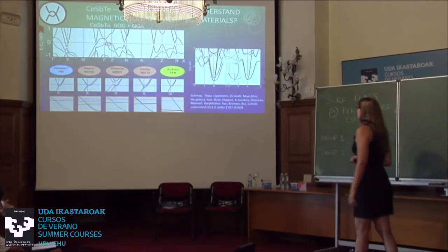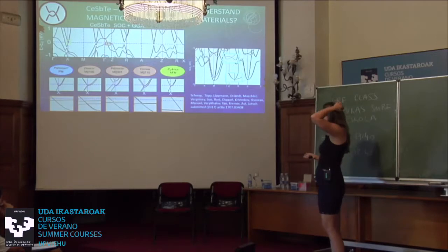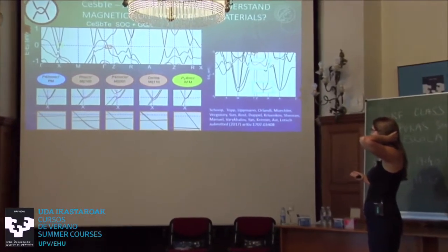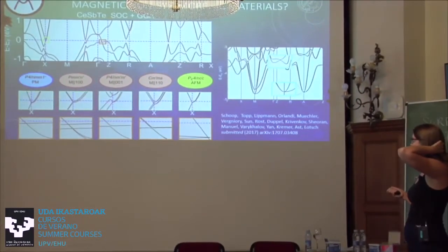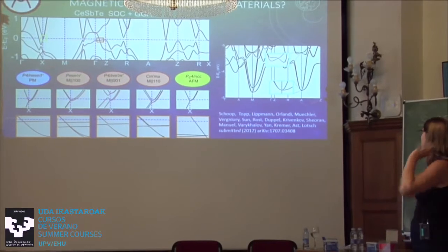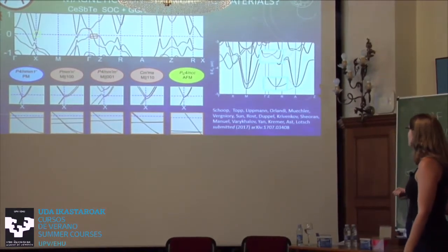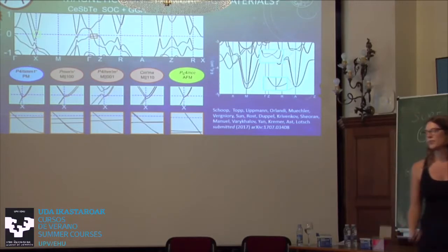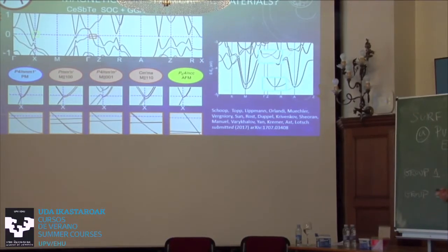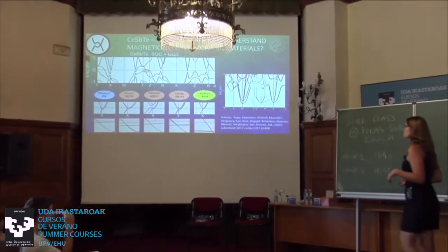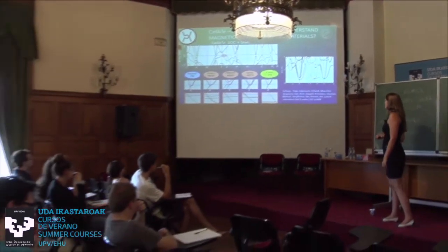And so here we could verify all the group theory predictions Maya did with the DFT. So we see the splitting, for example, here at the X point in twofolds, if we apply a ferromagnetic case, and we find the 8-fold degenerate point at the A point, sadly very far away from the Fermi level, so it's not yet applicable, but we're just starting with this idea of using antiferromagnetic order for this, so we can use this in the future.